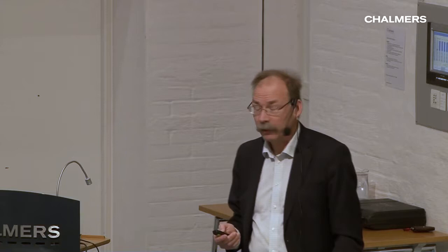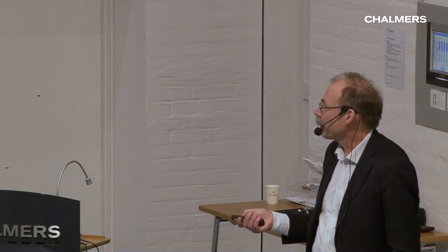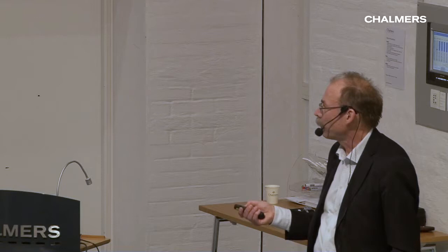If we go down one step to the fiber, we have used the fibers here for, what is it, 140 years approximately for different paper products. What we are doing now is to go one step below, into the cell wall of the fibers. And the cell wall of the fibers consists of cellulose, which is a glucose polymer. It's quite a large one. It's linear. And they end up as microfibrils. It's a number of polymers that are crystallized in microfibrils here. And these microfibrils are embedded in a matrix consisting of lignin, which is an aromatic macromolecule, and also some hemicelluloses, which also are carbohydrates, but much smaller compared to the cellulose.